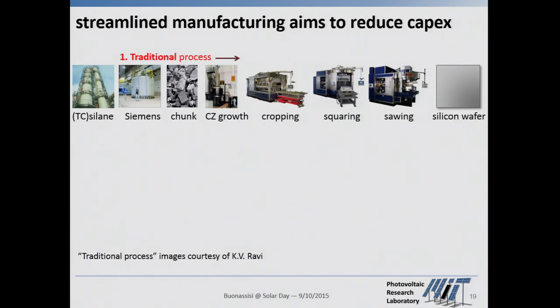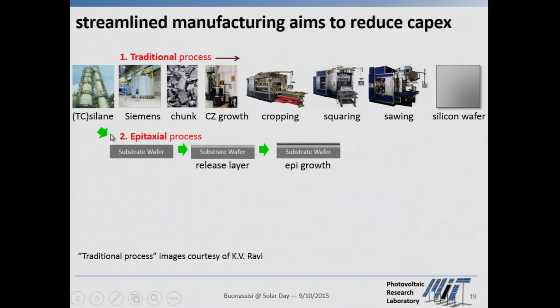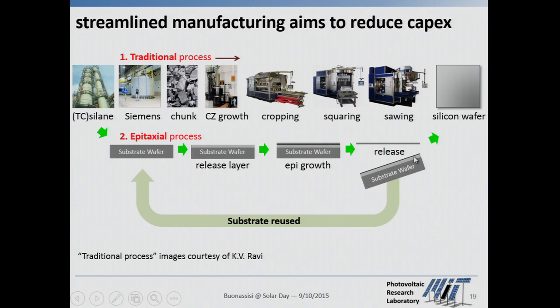So one company with which we've been collaborating, called Crystal Solar, has attempted to take the traditional process flow and streamline it and say, why don't we take the silane or trichlorosilane gas initially and deposit a thin epitaxial wafer on a substrate that's reusable, and we could separate that wafer so that we have the silicon wafer at the end of the process and then recycle the substrate and cut down the number of steps and critically the number of CapEx intensive steps. Also, by improving the grams of silicon per watt, you're reducing the trichlorosilane CapEx. It's an interesting feature of the polysilicon supply chain.